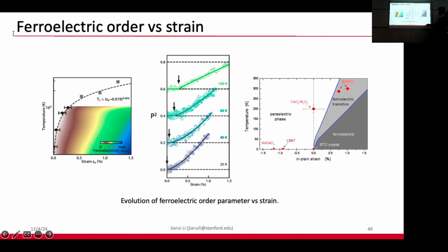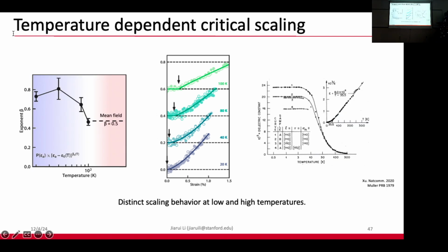So we perform a power law analysis to fit the critical exponents of this ferroelectric order parameter as a function of strain. And what we find is that the critical exponent beta is temperature dependent. At higher temperature, 100 Kelvin, it is around 0.5, and when we cool it down to 20 Kelvin, it starts to increase towards 0.7, 0.8-ish. And from mean field theory, if you do a Landau theory calculation of how the ferroelectric order parameter should behave as a function of strain, you would get 0.5.